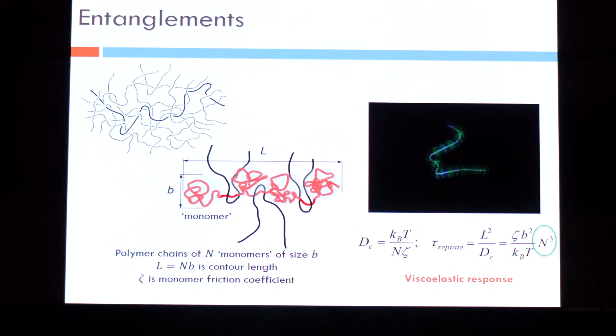So the way to understand these entanglements and their effects is to consider the bottom cartoon where you have these polymer segments between entanglements. So between two consecutive entanglements, the polymer is free to do what it wants. So it can move around, and typically these polymers, with their Brownian motion, move around and form a lump. So those circles that you see there with the coil inside it are those lumps which are there between two consecutive entanglements. But at the point of the entanglements, it is constrained. It can't move around too much because it is fixed by these entanglements. And that's how the polymer molecule would look.